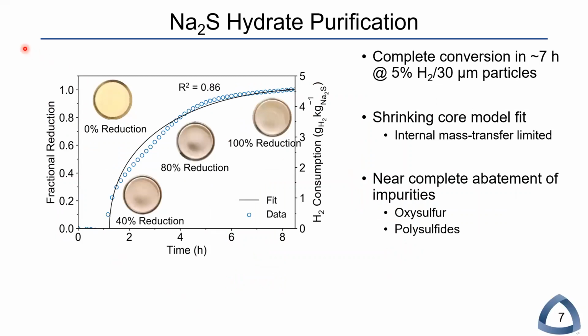Historically, this purification process has been conducted around 900 degrees Celsius with reaction times around 12 hours. However, for the first time, we've demonstrated that with optimized reactor design, this purification can instead be conducted at 400 degrees Celsius with reaction times on the order of 7 hours.